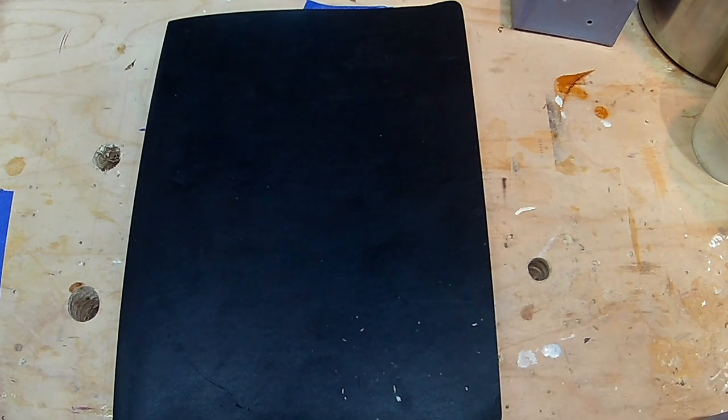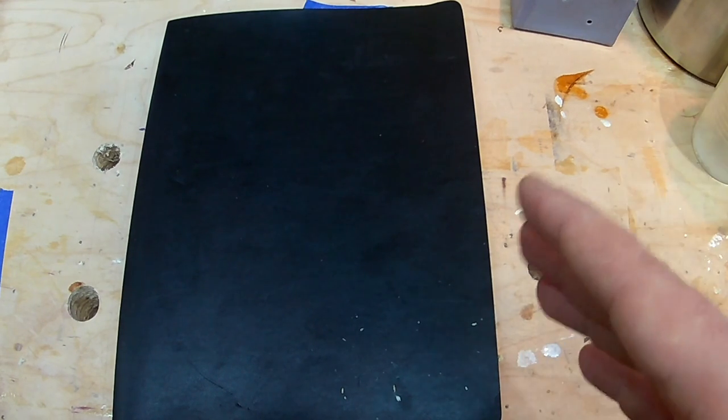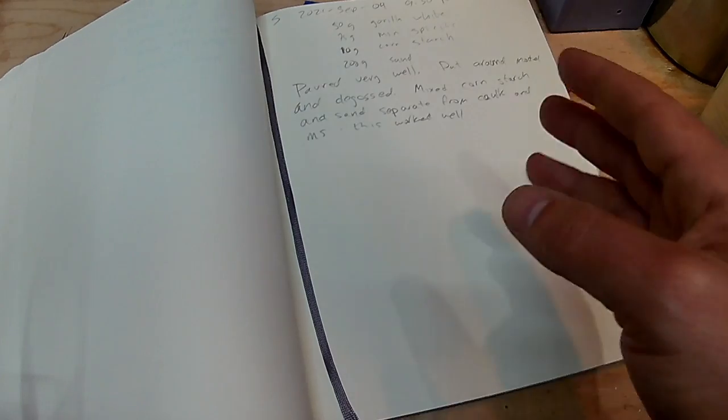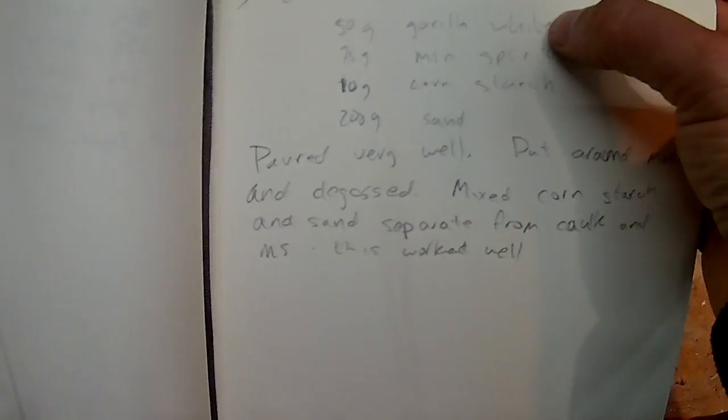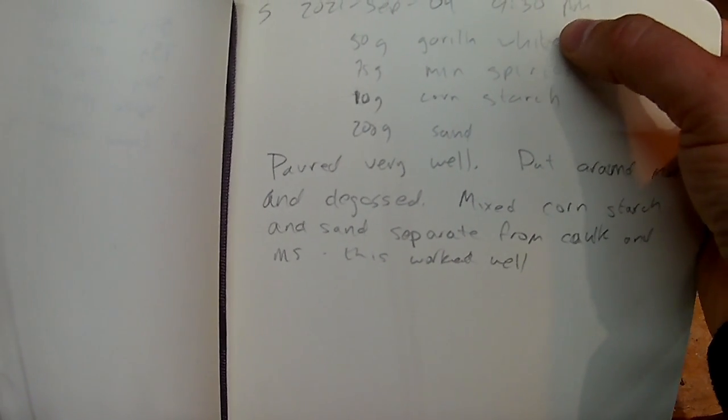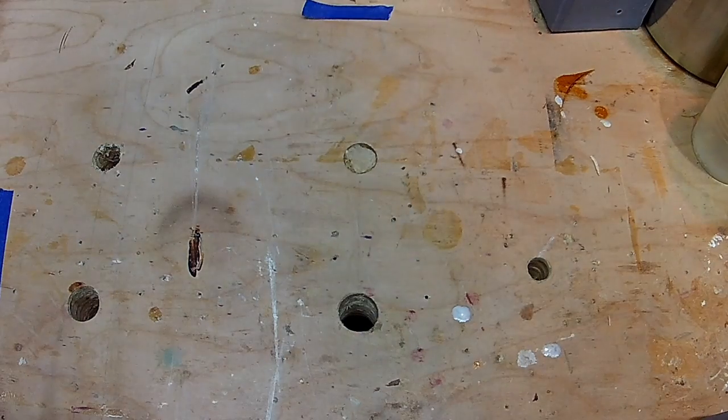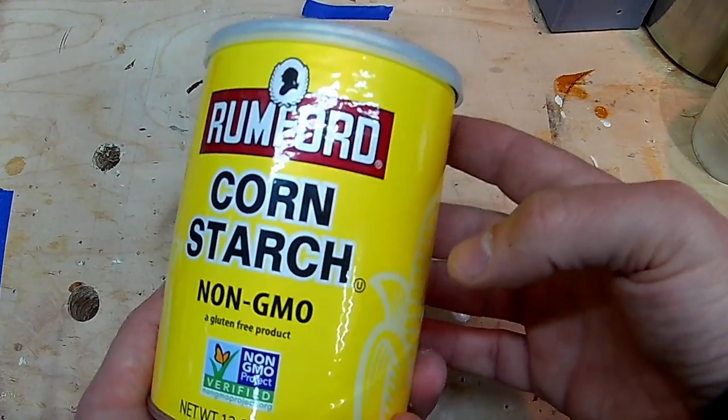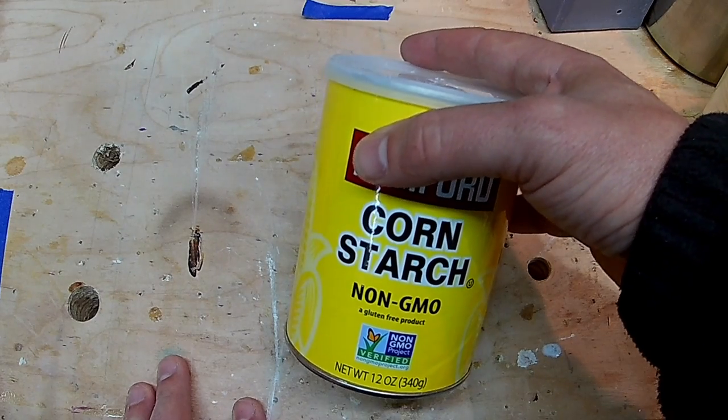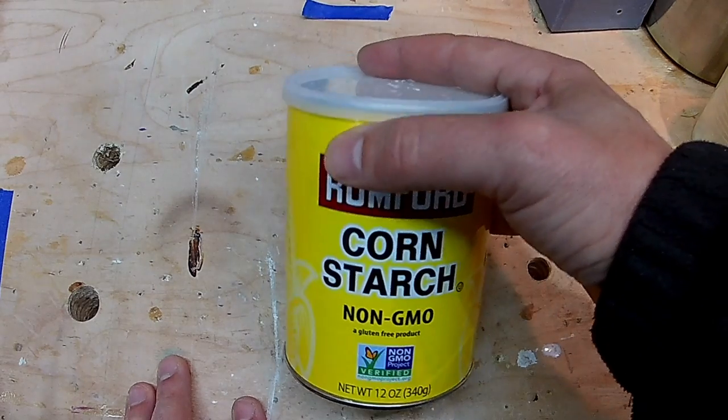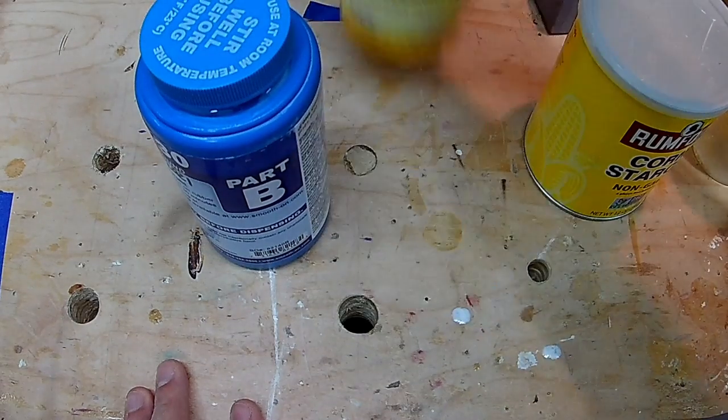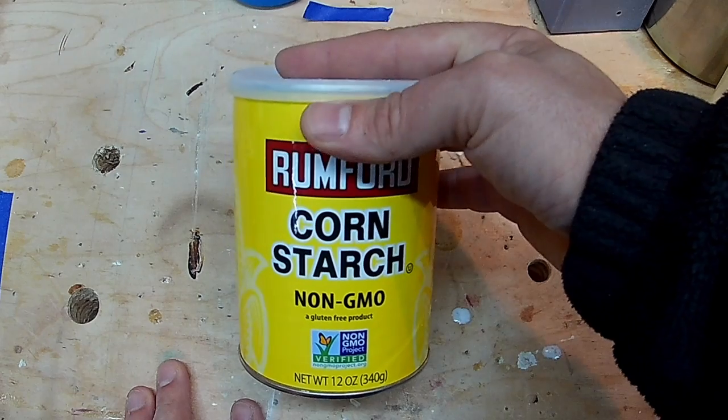Okay, so so far so good. The problem there was that it was taking a really long time to cure, like days and days and days to cure. Actually, let me just show you my experiments list here. I have them lettered up in the corner. You can see maybe that's FE and I'm all the way up to experiment QR. I think I'm on S now. Yeah, S is my latest one. So, I've pretty well got the formula done. And if you can see some of the things I've been doing there, 50 grams of Gorilla White, 75 grams of mineral spirits. That's 1.5 to 1. That makes a really thin mix. And then this next ingredient was the next thing I hit on. And I've heard about people doing this before. It's cornstarch. And so, this is just regular cornstarch that you would get just at the grocery store or whatever, 100% cornstarch. What I discovered, I mean, I didn't discover it, but it was new to me anyway. I knew people had been using this to make a sort of putty for molding. I don't really want a putty. I want more of a liquid like what you get with the two-part stuff. And what I discovered is when you add this, it vastly speeds up the cure. It went from taking three days until it was not gooey in the middle to being three hours, and it was all the way cured in the middle.